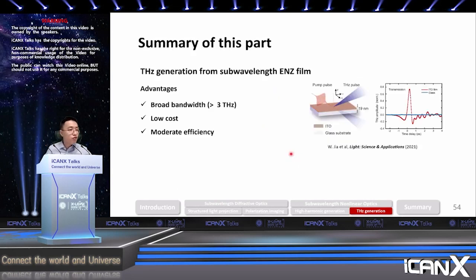So to summarize this last part, what we have shown is that we can generate a broadband terahertz pulse with this very simple sub-wavelength ENZ film, essentially made out of commercially available ITO glass, which can give you quite a large bandwidth, quite low cost, and a moderate efficiency.